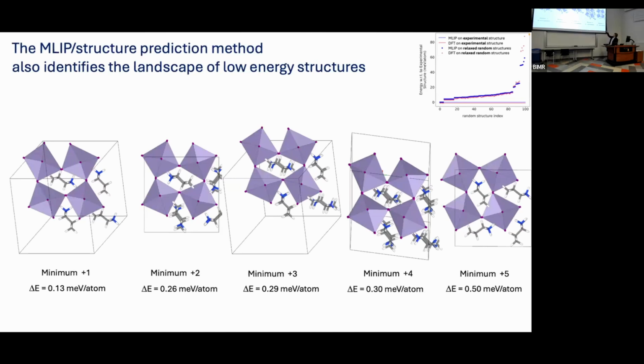What was interesting is, just as we observed here, that there are several different structures with slight permutations relative to each other that have very similar energies. So here I'm showing the minimum plus 1, 2, 3, 4, or 5. And you can see structurally, they look very different, actually. Mostly that's due to the swapping of the organic cation. So it's intriguing to us that their energies are very, very small, but structurally they look very, very different.